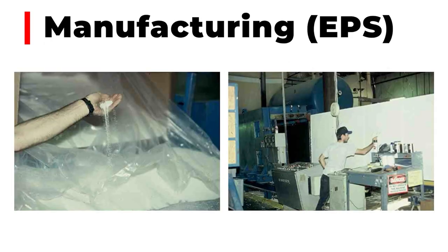How are they manufactured? The closed-cell foam — predominantly EPS — starts out looking like sugar or salt. We apply steam to it, which releases pentane gas, the blowing agent that all plastic foams have. The foam expands into little tiny beads that trap air, preventing the movement of air or energy through the wall. Those beads are put into a mold with more steam, turning into a solid block of foam, which is then sliced into smaller pieces using hot wires with voltage applied — because EPS is a thermoplastic that melts when heated — creating a nice smooth slab.